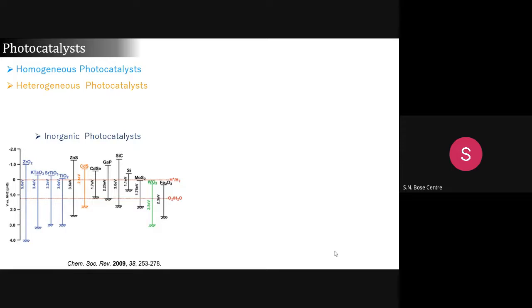So all this material has very different band gap, and based on their band gap, their efficiency changes, because of the driving force for the hydrogen evolution. So you can see, suppose for the zirconium oxide, the band energy is well above the hydrogen at a particular pH. So it can very easily give its electron to reduce the hydrogen.